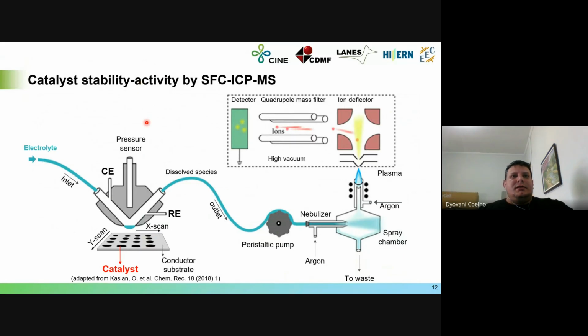There they use an elegant approach, where they use a scanning flow cell to perform the electrochemical measurements and track the electrolyte composition in ICP-MS. So they are using a scanning flow cell to verify a lot of catalyst spots, for example, just changing catalyst composition and things like that. And online, they track the catalyst degradation using a really sensitive technique, which is ICP-MS.